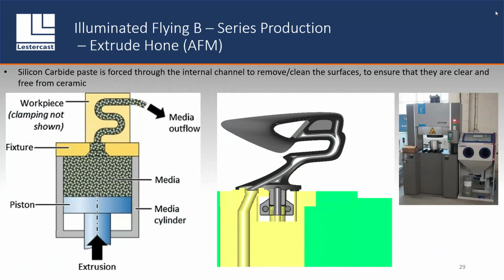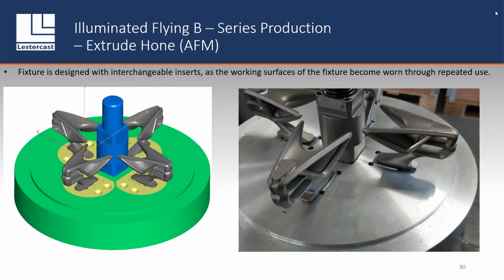The extrude honing process, it's an abrasive media inside a pressure vessel. So this is the machine. Inside here, we have the abrasive media, and the components are fixtured up. And basically, the abrasive paste is pushed up through the cavity and then dragged back through again. So it's a bit like sandpaper in a casting, but it's quite automated. So again, a 4-station fixture for the AFM side of it.